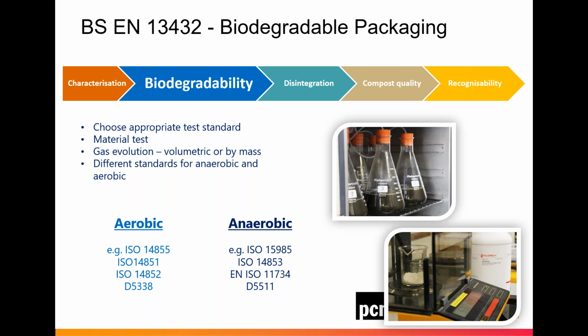So if your biodegradable material is intended to be used for composting, then it should be tested with ISO 14855, where we mix the biodegradable plastic with industrial compost, and we monitor the CO2 being produced from the reactors. For water, sludge and wastewater treatment works by degradation, we use the ISO 14851. That's mainly for water-soluble products. Or the ISO 14852. The difference between these two standards is the method you use to measure the CO2. And obviously, we have the corresponding ASTM standard, which is the ASTM D5338.